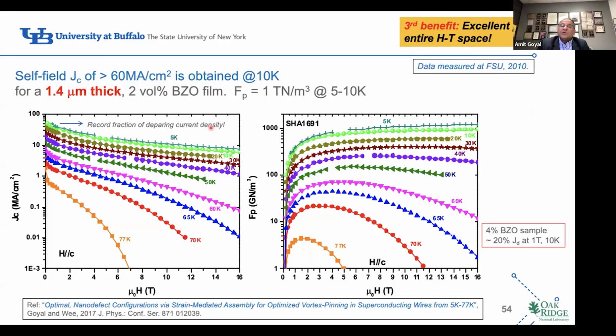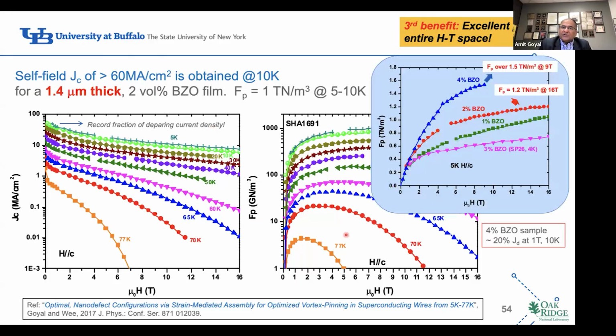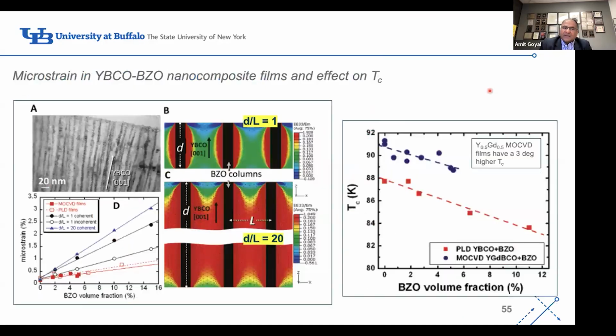And this could only happen if you had a lot of point defects. And there's something called a pinning force. And it turns out that the pinning force went to tera-Newton per meter cube, which is absolutely fantastic. So let me just tell you why we get these point defects.